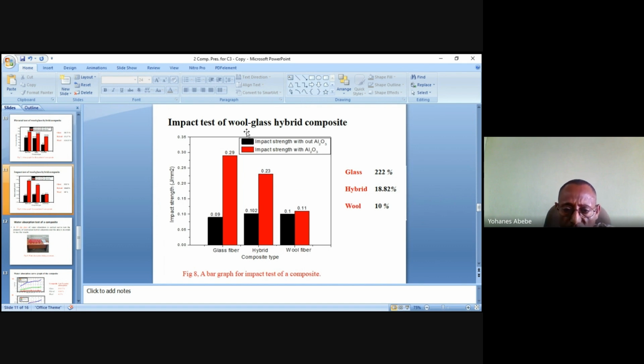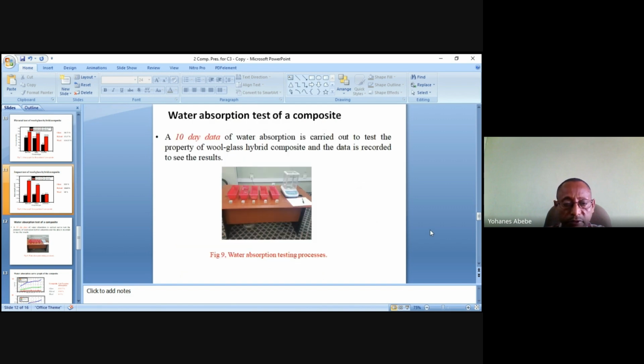The impact test of this composition also shows that the glass fiber composite has some improvement as a result of nano application. The impact strength improved, and so for the wool fiber also, and for the hybrid of glass fiber and wool fiber, improvement was also observed. So in terms of percentage, the glass fiber composites have 220%, and the wool fiber is 10%, and the hybrid is 18.82% improvement in results from the mechanical tests obtained from the UTM.